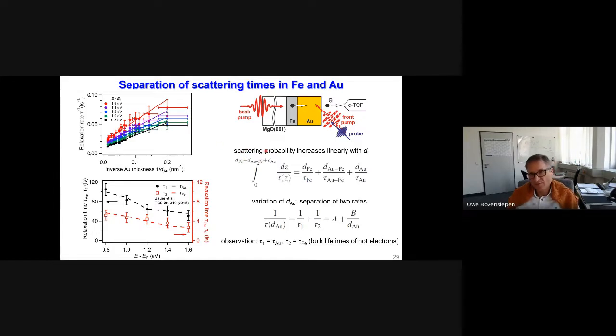So in principle, the scattering probability increases linearly with the film thickness the electron propagates through. And in fact, we consider here scattering in the iron layer thickness, in the gold layer thickness, and in the interface region. And then you can basically integrate this, considering the inverse relaxation time at the respective constituent, which is then the scattering rate. And these rates basically add up independently as suggested by Matthiessen's rule, because spatially these regions are separate. And for variation of the gold layer thickness, we expect to separate two decay processes. And we can simply argue that we have the thickness-dependent relaxation time, which has one contribution in iron and one contribution in gold. And let's check whether this in fact holds.